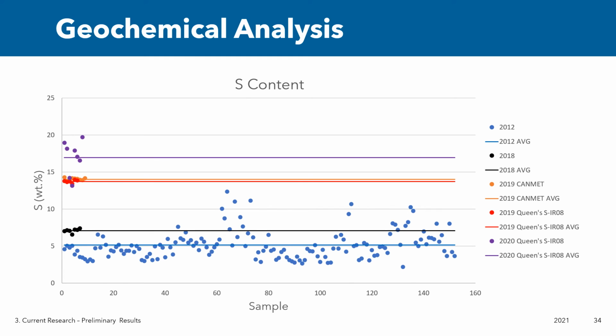And here you can see that the range in sulfur values for the 2012 sample do not even reach the values of the 2019 and 2020 samples. These results show that there is a greater range in element contents than previously expected, which influences the results of the oxidation and flotation experiments.